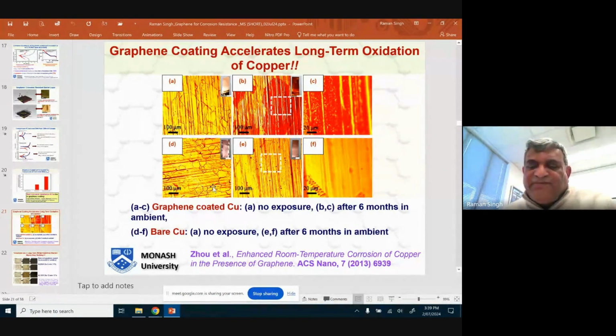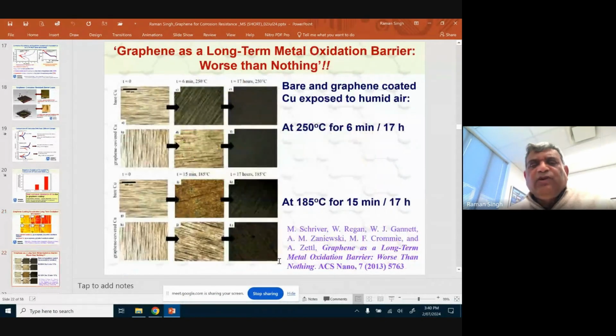But around the same time, in 2013, just a year after our paper, there came a paper which says graphene, in fact, accelerates corrosion. Instead of giving corrosion resistance, it accelerates corrosion. And it was published in a very reputable journal, as you can see. And as if one was not sufficient, there was another paper published in the same journal. And see the title of the paper, Graphene as a Long-Term Metal Oxidation Barrier: Worse Than Nothing. What it's saying is that if you don't have a coating, it will behave better compared to having the coating.